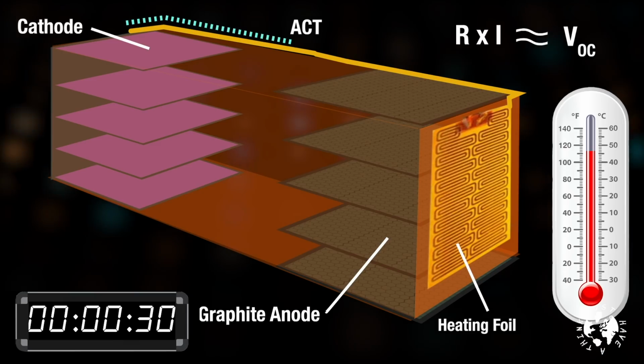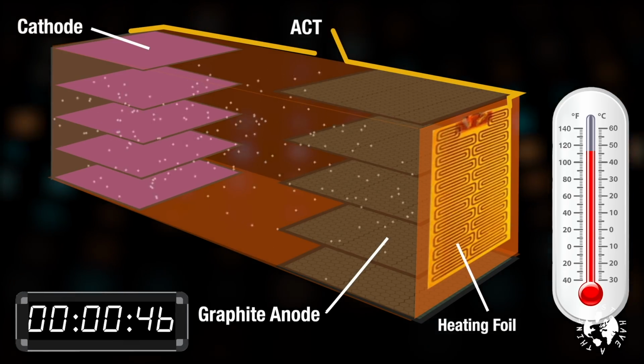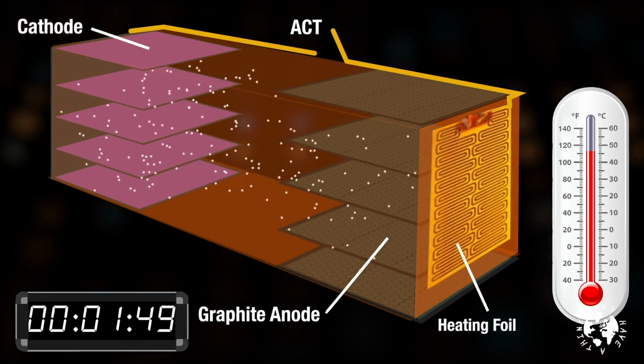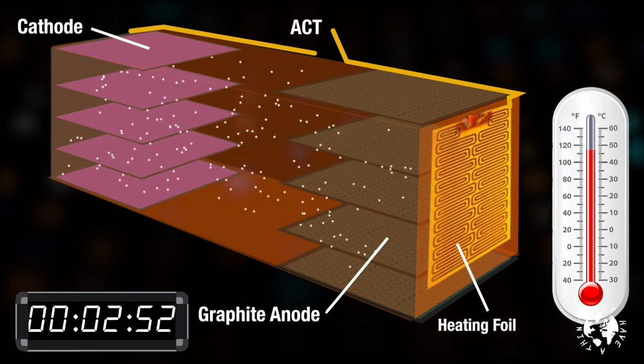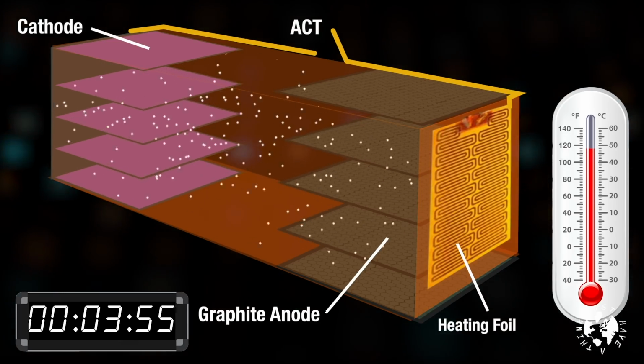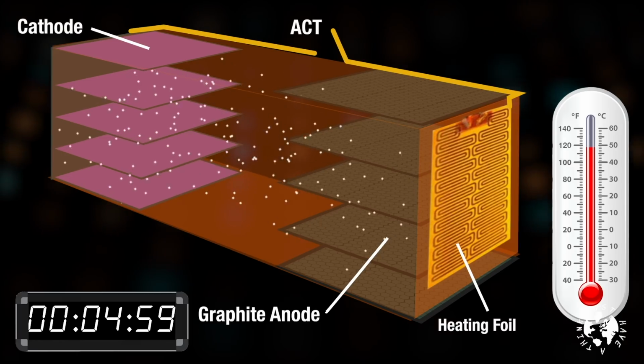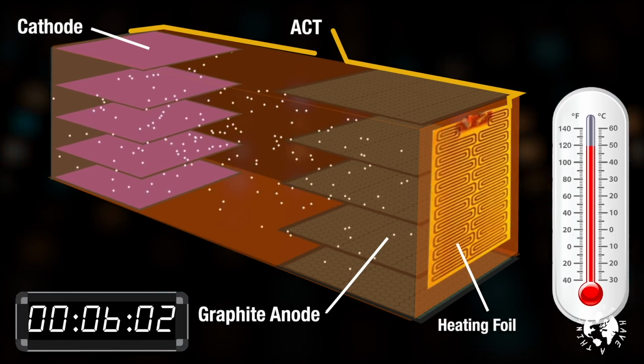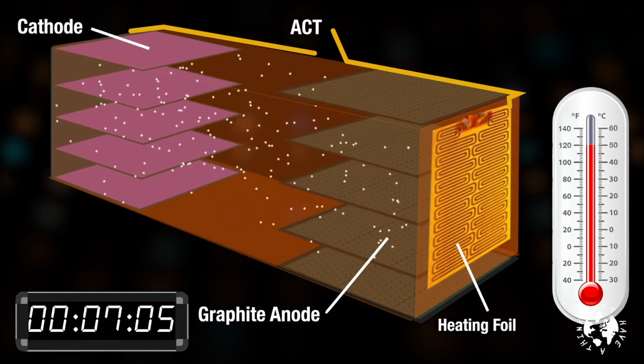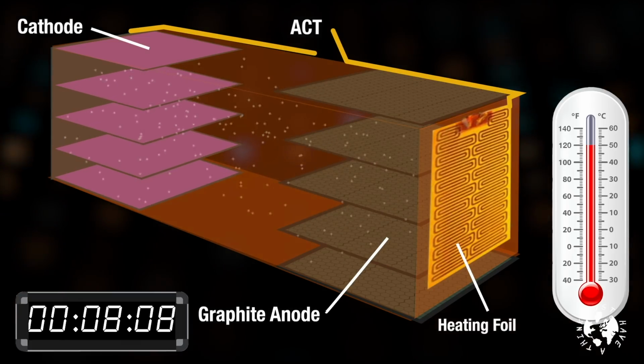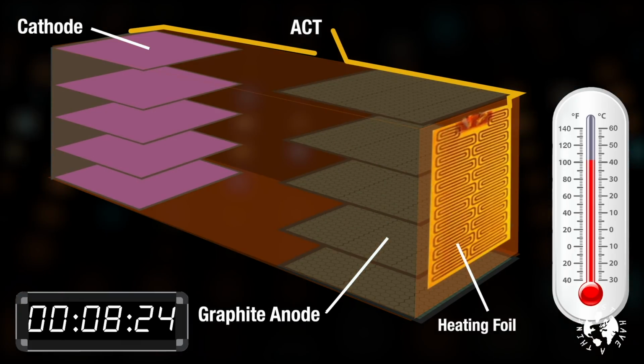At that point, the ACT current is switched off, and all of the energy in the circuit can now flow into the cell to do the charging. The total charging time to get to 80% state of charge for the 9.5 amp hour plug-in hybrid battery that was selected for the demonstration, including the 30 second heating stage, was 503 seconds or 8.4 minutes.